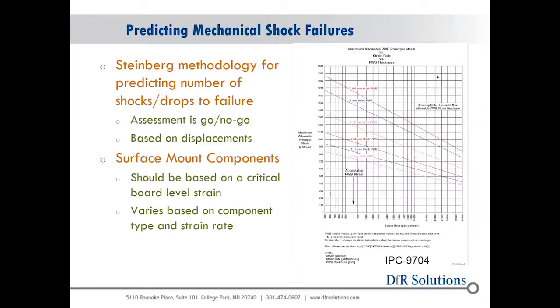When we get to simulation and prediction of mechanical shock failures, we're going to start with the old school technique using Steinberg methodology for predicting number of shocks and drops to failure. Really, it was more of a go, no-go type criteria based on displacements, which when you think about it, really makes sense, because as soon as I get into a low cycle fatigue type of behavior with a shock event, there's a good chance that I'm going to break something due to overstress, because the yield stress of solder is close to the breaking stress for a lot of these materials. So I like the go, no-go approach.